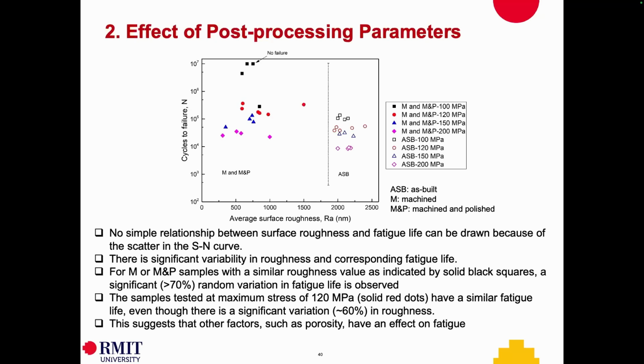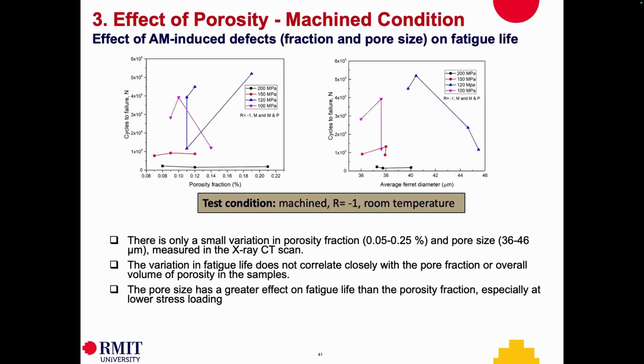It can be two ways. Significant roughness variation can produce similar fatigue life, or quite different fatigue life for very close roughness. So we can have a not really good correlation, as you see with the diagram. Very small variation of porosity fraction and pore size.